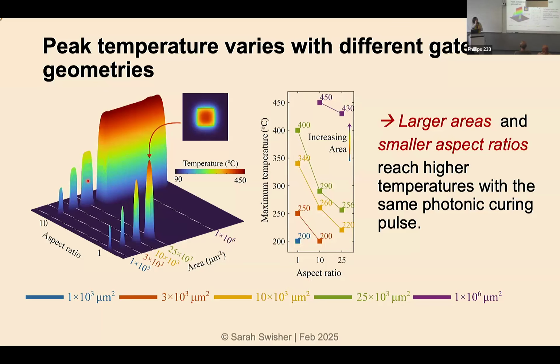And so all of a sudden, with this large area tool, we really have to think about how the device dimensions are going to affect their curing temperature. Because as you can see here, we had some devices in this design of experiments that reached 450 degrees. And we designed the experiment such that some of them should have a curing temperature of only about 200 degrees, which means they shouldn't work, right? Those devices are not going to get converted into the oxide that we want.